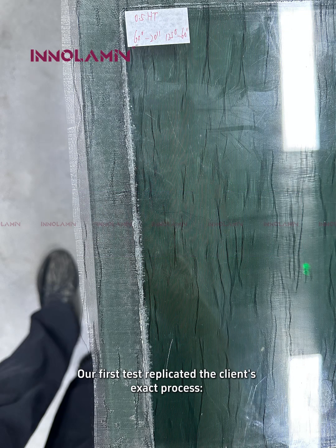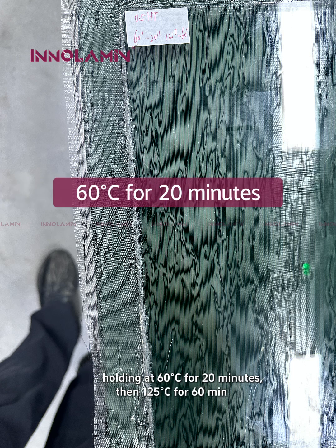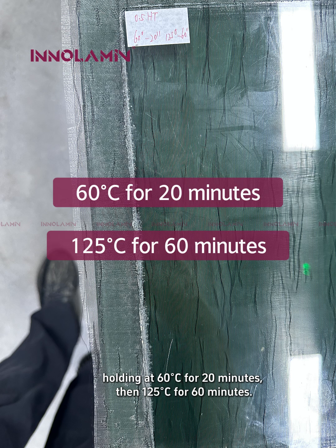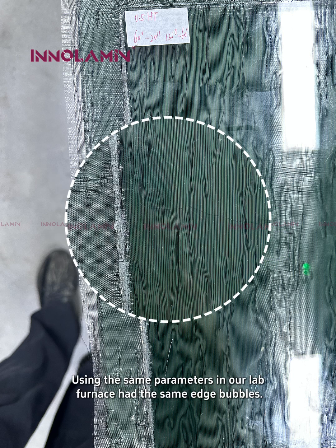Our first test replicated the client's exact process, holding at 60 degrees for 20 minutes, then 125 degrees for 60 minutes. Using the same parameters in a lab furnace had the same edge bubbles. This ruled out equipment faults, directing our focus to optimizing the process parameters.